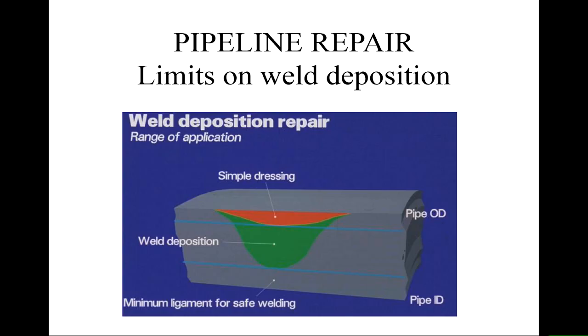So when we're talking about repairs, what are the limits on what we can do? Well, if we're looking at a simple dressing case, we're looking at probably 10, 15, 20% maximum of the thickness of the wall. If we're looking at weld deposition, we can maybe go up to 60 or 70% of the thickness of the wall, remembering that that must include the penetration of the weld. So the weld deposition here mustn't go more than that 60 or 70%. So there must be some sort of ligament, some minimum ligament left of the pipe remaining underneath the weld for any process to be acceptable. And different standards have slightly different numbers in those cases. And you can do qualification tests to prove how much you can weld with a particular process, exactly what that will be.